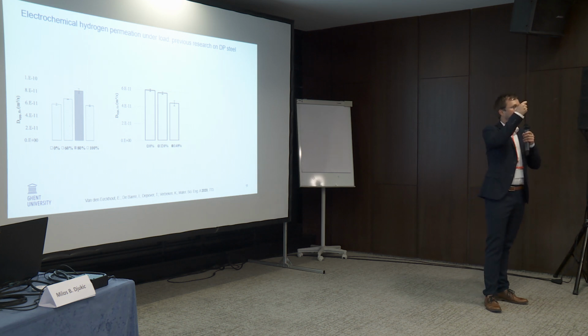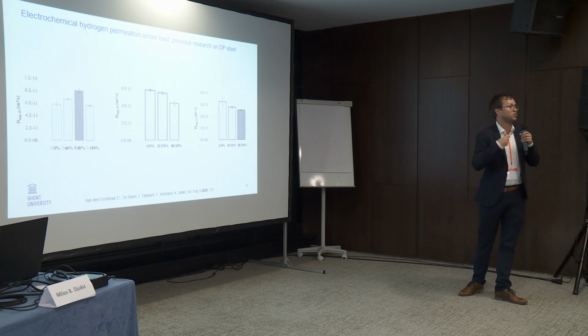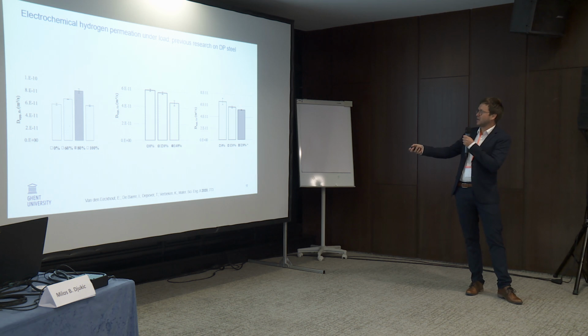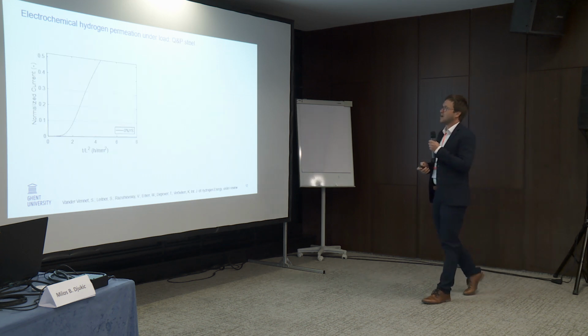After that 120, we also release the load. And then your elastic is recovered, right? And the only contribution is only the plastic. And then you can see, indeed, that you drop a bit more. The diffusion coefficient drops a bit more because your contribution of the elastic part is gone. And this is a proof, indeed, that the elastic strain can increase the diffusion coefficient in these materials. Quite simple materials, dual phase, ferritic, martensitic.